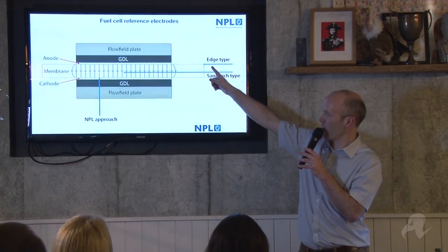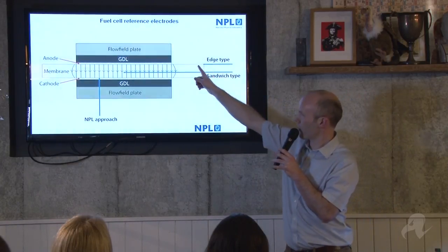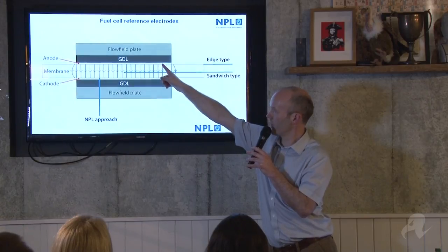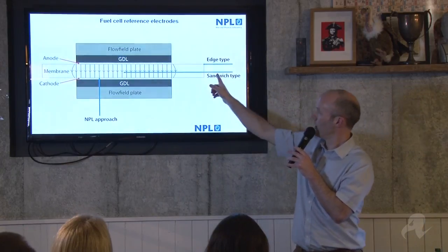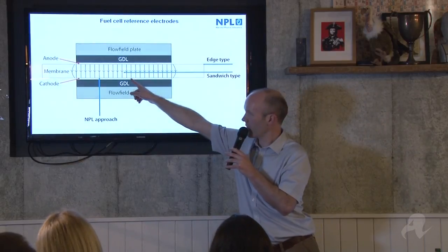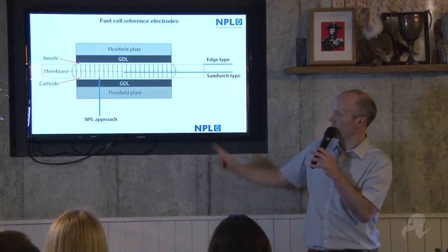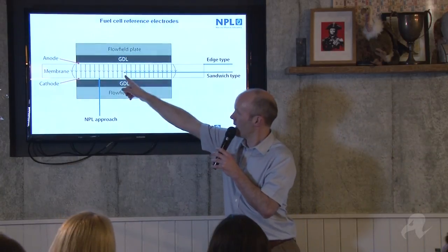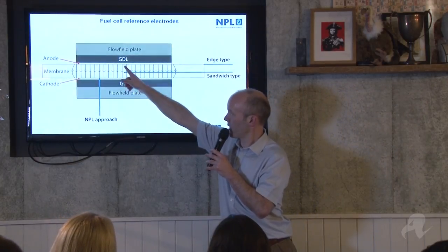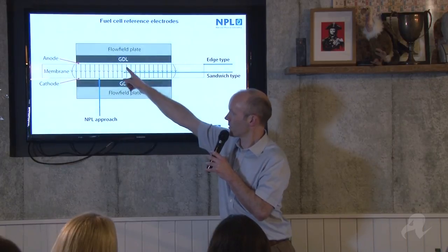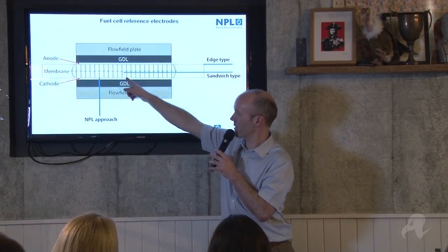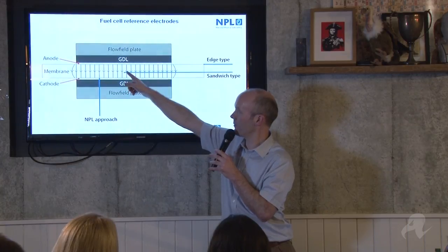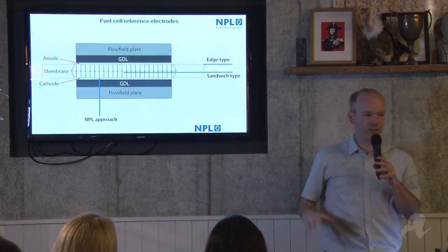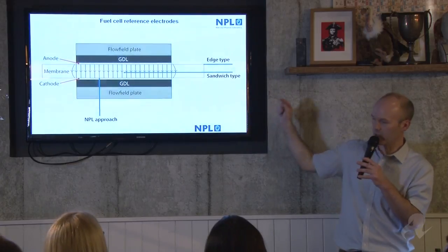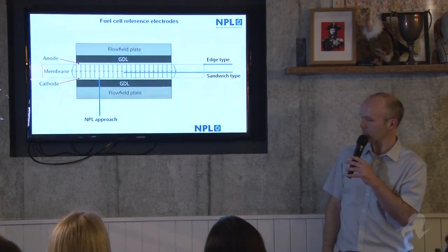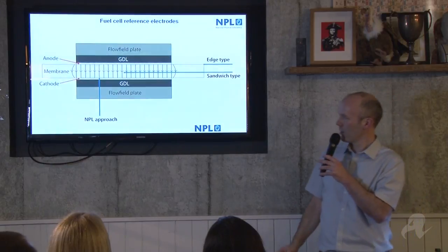The edge type one is too far away, so there's a big potential drop between here and the potential of the electrodes that you're trying to measure. The sandwich type one is better, it's closer to the action, but it's perturbed. There is a potential drop here, so it doesn't take that into account. It needs to be right up at the electrode surface to avoid that. But also, the presence of the reference electrode itself interferes with what you're trying to measure, because it's right there inside the membrane. So our approach was quite simple.